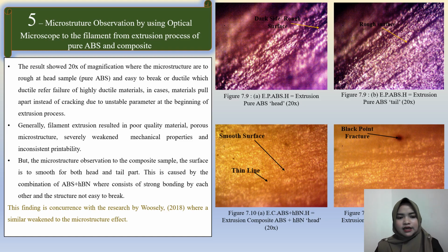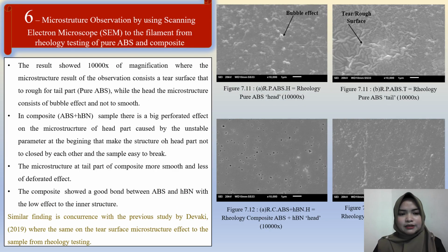This finding is consistent with research by Woosely, 2018, where a similar result was seen in the microstructure. Number 6 is microstructure observation using a scanning electron microscope (SEM) on the filament from rheology testing of pure ABS composite. The results at 10,000 magnification show that the microstructure of the tail part of pure ABS has a rough surface, while the head consists of bubble effects and is not too smooth.